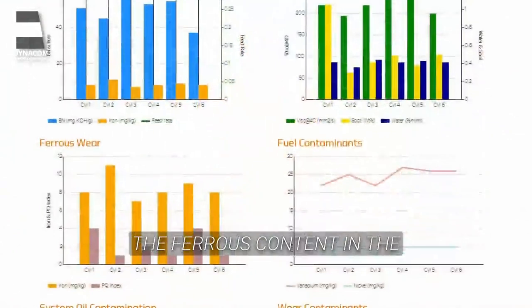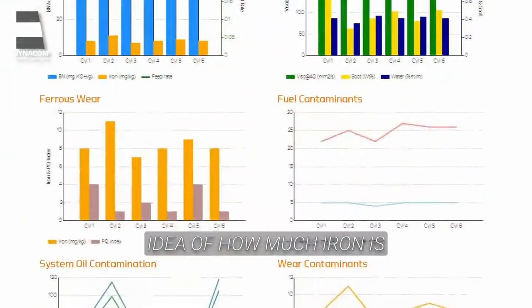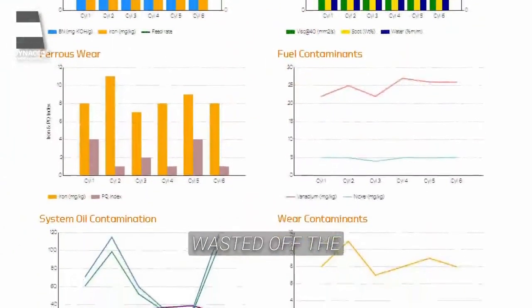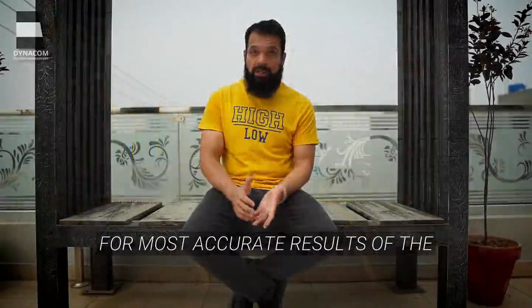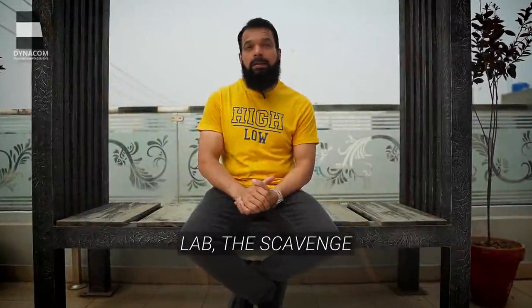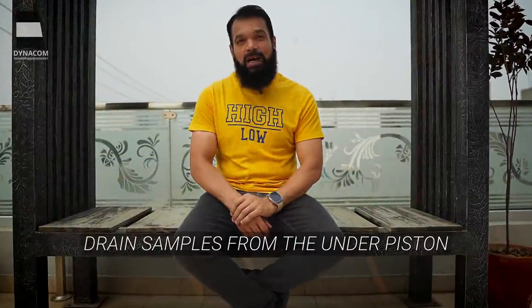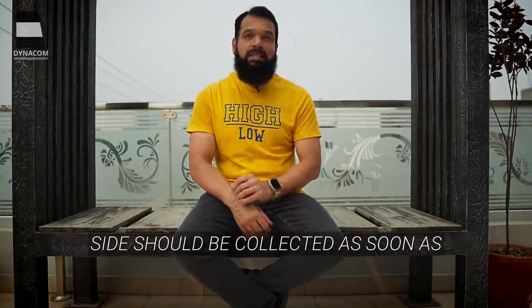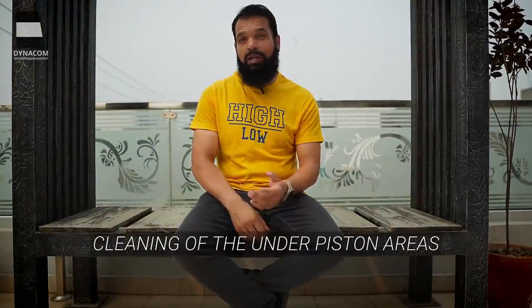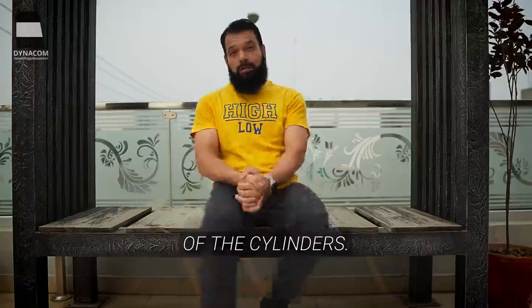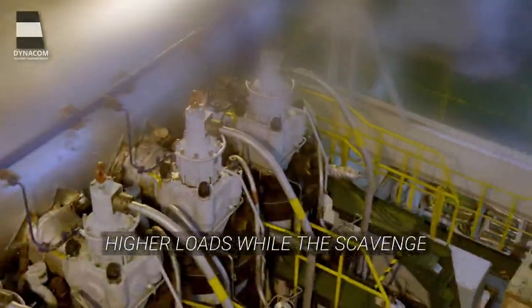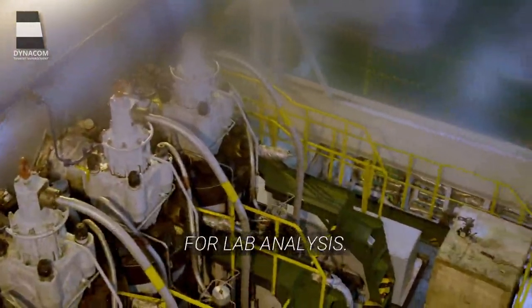The ferrous content in the scavenge drain oils gives a good idea of how much iron is wasted off the cylinder liner surfaces. For the most accurate results of the scavenge drain analysis by the lab, the scavenge drain samples from the underpiston side should be collected as soon as possible after thorough cleaning of the underpiston areas of the cylinders. Engines should be running at higher loads while scavenge drain samples are collected for lab analysis.